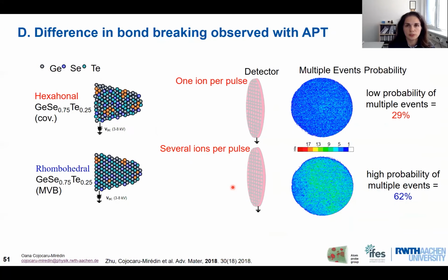For that, we took two different compounds, and we compared the evaporation process in the atom probe, the bond breaking process. What we have observed is that if we take hexagonal germanium selenide telluride, which is a covalent compound, and we have a laser coming on it, we see typically a high probability of single events and a very low probability of multiple events. Now, if we take a rhombohedral compound, which is supposed to have these particular bonding properties, when we have the laser coming on it, we have typically a very high fraction of multiple events. This is about 62%. We see also nicely that these multiple events are homogeneously distributed over the detector event histogram.